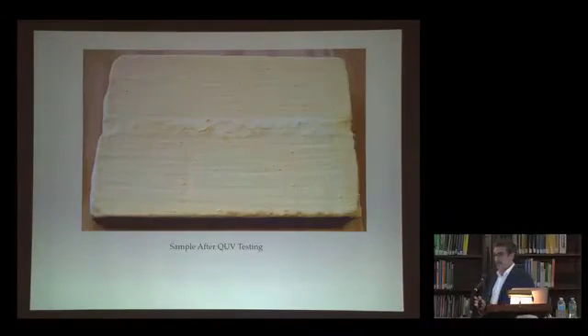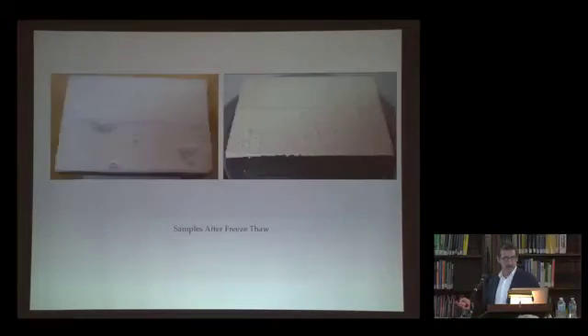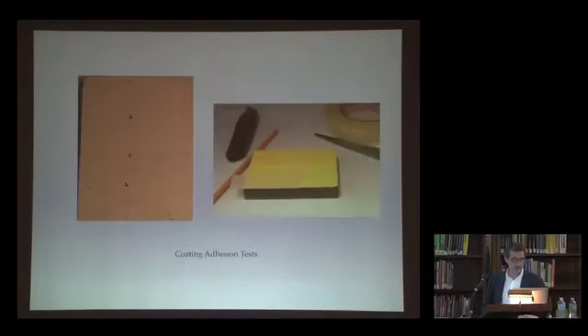So what was absolutely shocking to all of us was that after not so rigorous a test, we started to see the crack fillers expand. They started to break, the coatings started to bubble, and this one was from the QUV. From the freeze-thaw tests, the others the same thing, larger bubbles, different ways of expanding. And this is just one of these optical illusions. Those aren't going in, they're actually coming out. But again, if we had gone on to a manufacturer, it could have been problematic.